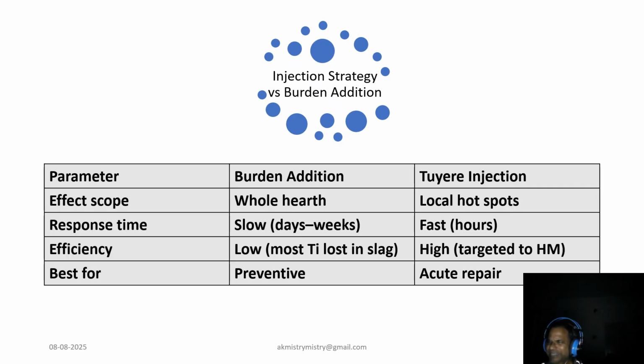Now, there are two main ways to get titanium into the furnace. First, adding ilmenite or rutile to the burden. That gives you a slow overall hearth enrichment, good for prevention, but it's inefficient. Most Ti ends up in the slag and it can take weeks before levels in hot metal rise. Second, tuyere level injection. Here you can target a hotspot, see a local effect within hours, and use less material for the same production. In these plant trials, discontinuous and high rate injection during tapping gave the best TiCN buildup. So this is a very important outcome of this combined study.